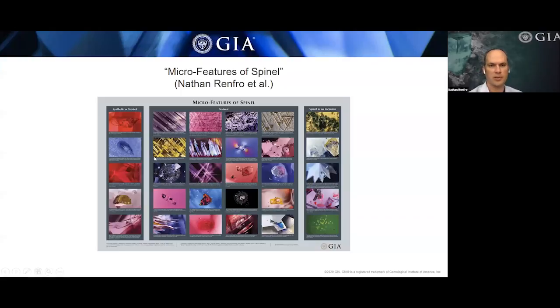And so on the left side of the chart, we have a few examples of synthetics or treated features that you might see. Since there's not a lot of treatments in Spinel, there's fracture filling and maybe cavity filling, that's about it. And then we have examples of flux Spinel and flame fusion Spinel here. And then in the center portion, we have the vast majority of the photomicrographs, which are inclusions that you might observe in natural Spinel. And unique to this chart compared to the charts that we've done in the past is we also had a few photomicrographs of Spinel as an inclusion in other gemstones. And so you have Spinel in garnet, Spinel in sapphire, Spinel in ruby, Spinel in peridot. So Spinel is a little bit unique in that way.